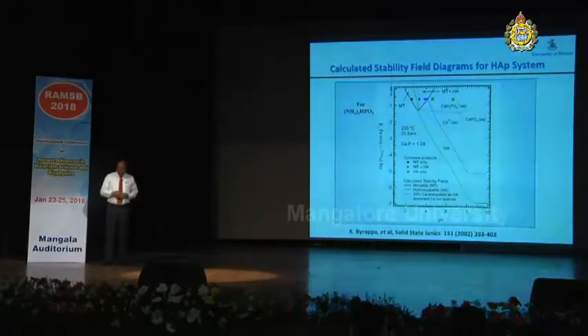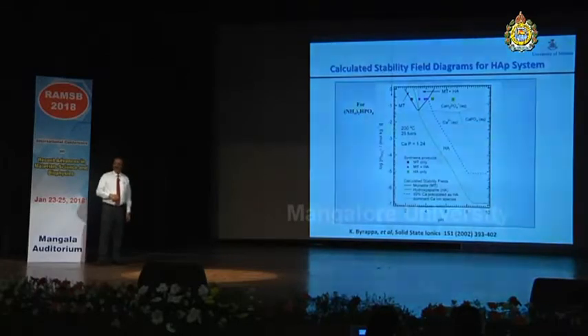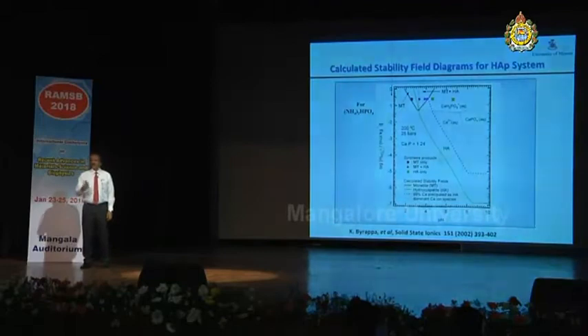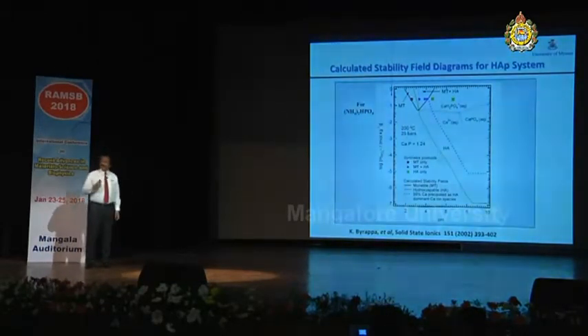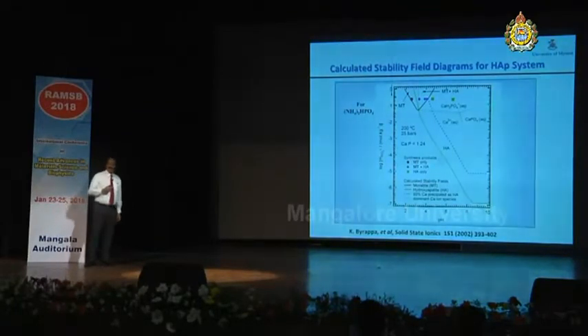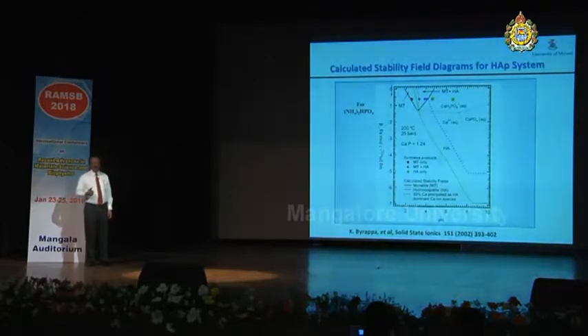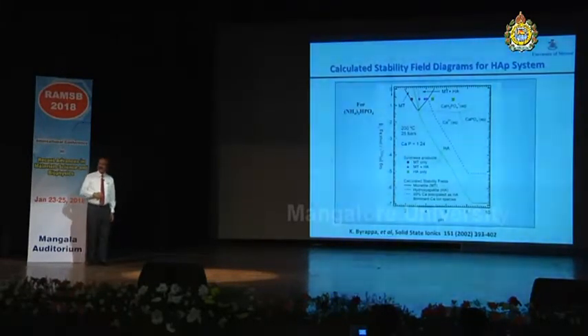Well, if you take very expensive rare earth compounds in your experiments, and if you do not get in your product all the raw material that you have taken, then it's going to be a big loss and very expensive. In order to avoid that, the yield diagrams would help you. Whatever raw materials you take, all of that would be converted to the product which you desire to crystallize. So about 99.999% of the raw materials can be converted to the final product designed by you. And this is the advantage of these stability field diagrams. We also call this thermochemical computation and the yield diagrams.